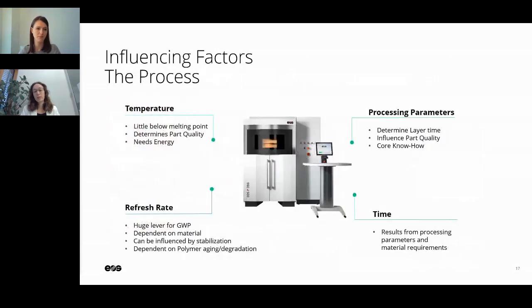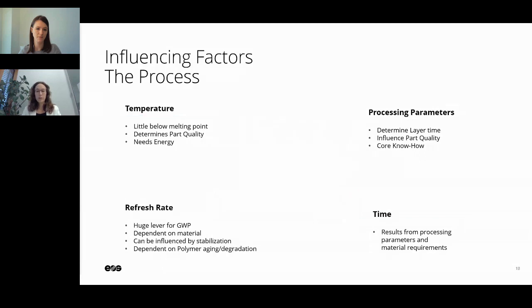Going to the next slide, we now have our polymer powder, and it's now processed on the laser sintering system. And there are several different things that actually influence the power consumption of the system. That's the temperature on the one side, because as you might know, it's a hot process, and we're processing the plastic powder at a temperature a little below the melting point. Which temperature we're using to produce the part determines the part quality, and of course it needs a majority of the energy.